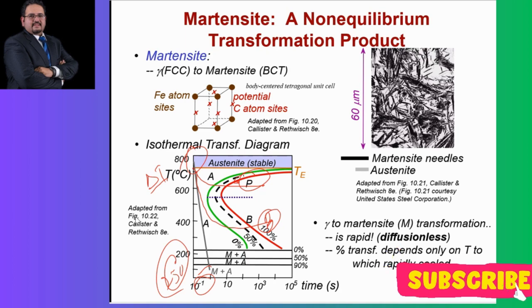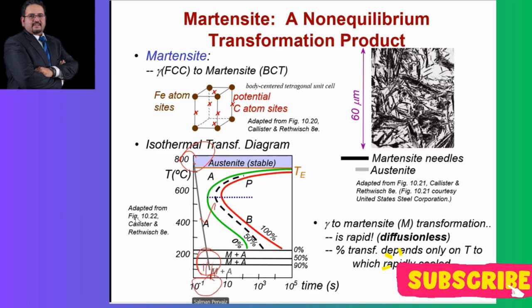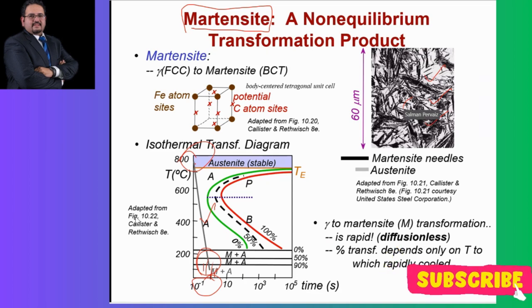So which operation is happening here? It was above 727, and quickly the temperature dropped and came into this region near room temperature in a very small time. This means the structure you get this time is martensite. Martensite under the microscope has a needle-like appearance. You see that it's not like layers, you will see needles there, right? That needle is related to the carbon content. It has a mixture of austenite, and the needle structure is the martensite structure.